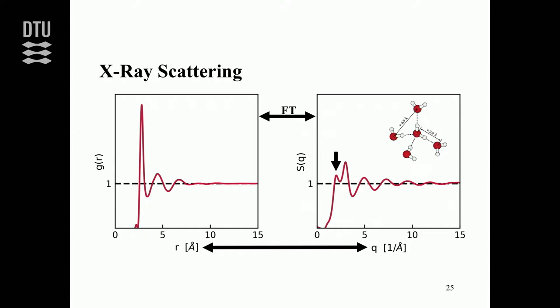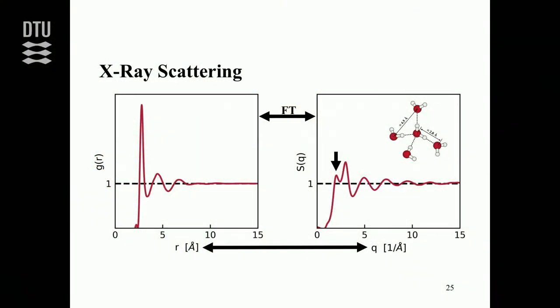Maybe to put that in another context, if you take any solid, let's say a metal, even a face-centered metal, it has 12 nearest neighbors. So would an argon liquid have 12 nearest neighbors. So that's more high packing. Ice or low density has only 4. So that opens a lot of space. And the reason for these 4, we can see here, is the directionality of the hydrogen bonds. That is very directional here, so to speak.